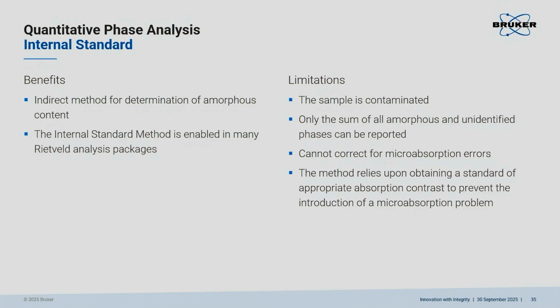By the way, if you add an internal standard, that's also something people tend to miss. They may add a microabsorption problem. Now, before you add a standard, first check the absorption coefficients. Does the mass absorption coefficient of your spike material fit to your sample? Or you add an additional microabsorption problem.